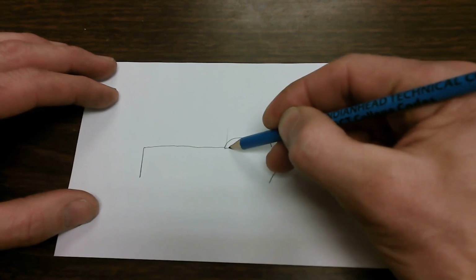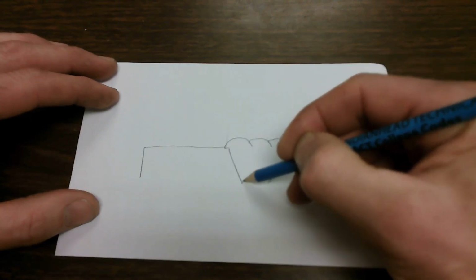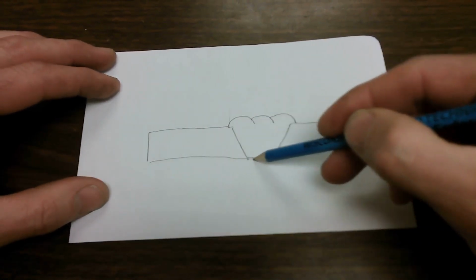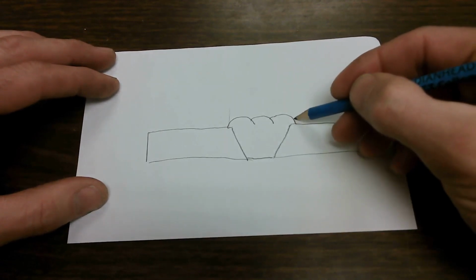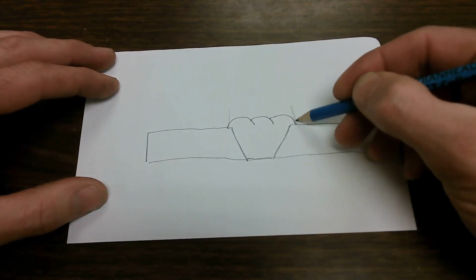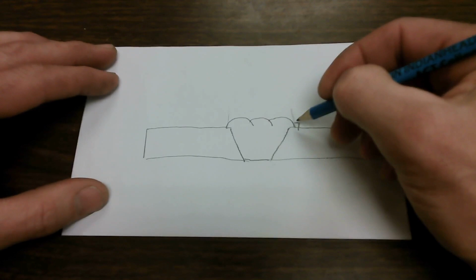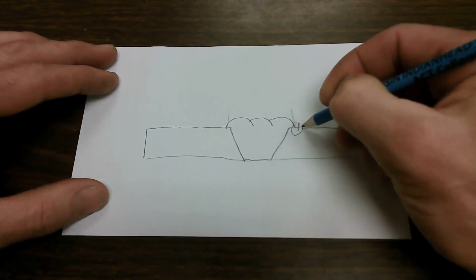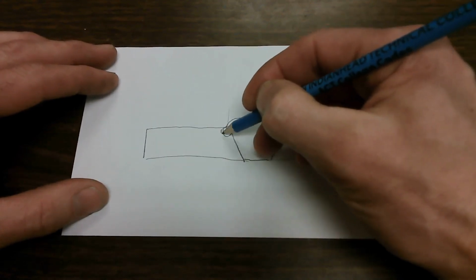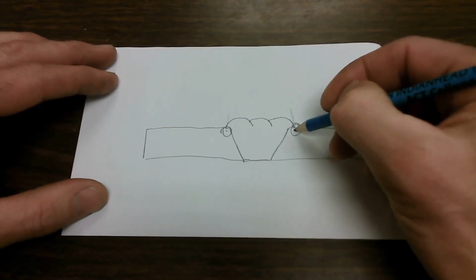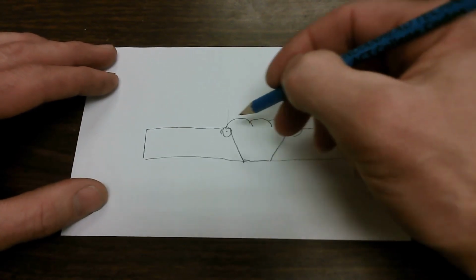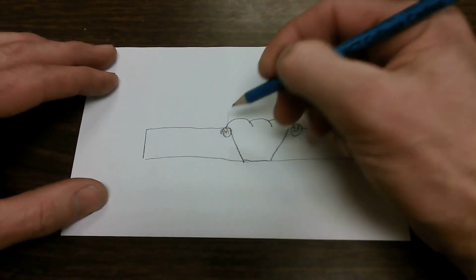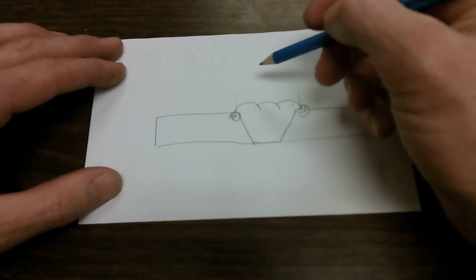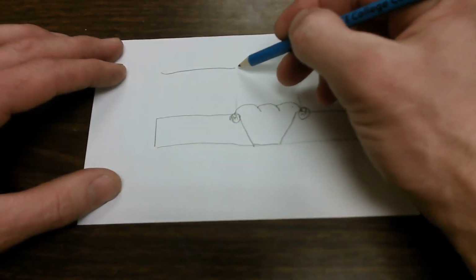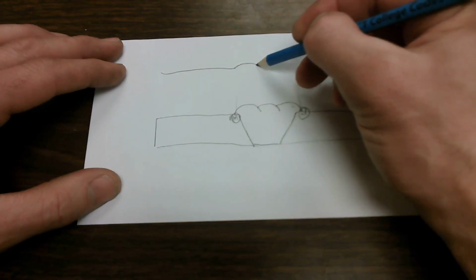and I'm just making the original joint, which was a V-groove in that case for the vertical one. So the steeper this angle, the closer this gets to 90, the more stress is going to be applied right here at the toe of the weld, right in this location. As the weld bead cools and shrinks, massive amounts of stress build up here. As opposed to, say, a weld that has maybe a little lower profile.